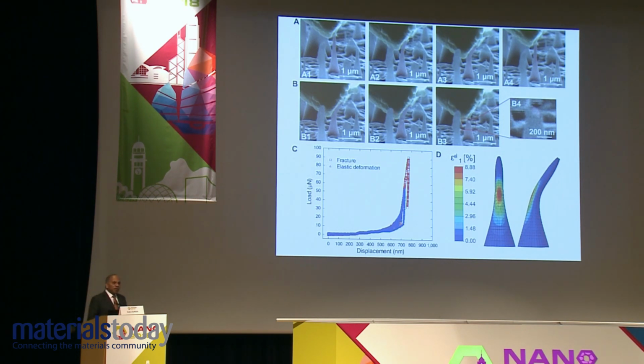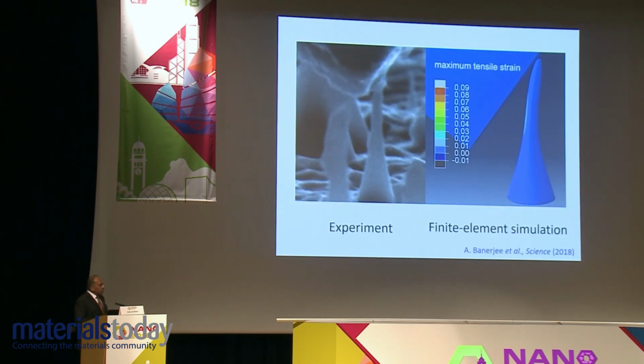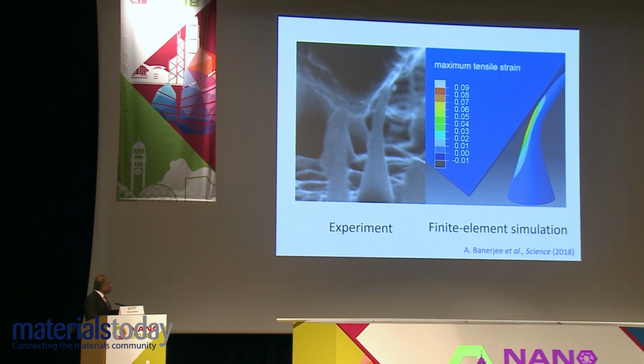And what is plotted here is the maximum elastic strain. In this case, it's a tensile strain in different colors. At the maximum point on the tensile side of bending, the strain is of the order of about 9%. So essentially, with diamond, we can deform it at the nanoscale, which you cannot do at macro or micro scale, locally to a maximum strain of up to 9%. That's what this shows. Now you see that in video, both experiment and simulation.